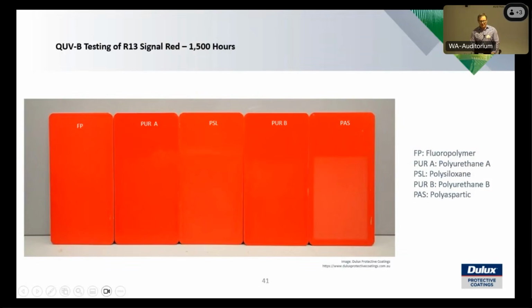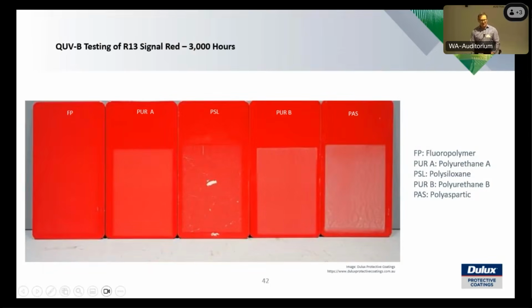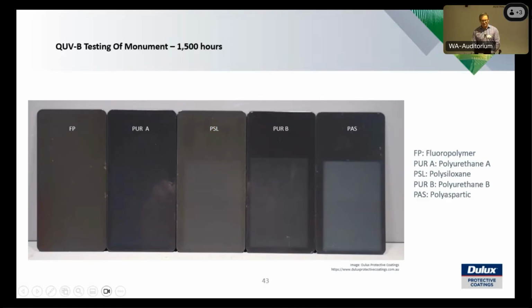We get to the signal red after 1,500 hours. As you can see, that visual there shows the signal red is still looking pretty good with the fluoropolymer. Hardly any change at all, and the polyaspartic is just starting to chalk up a little bit there. The 3,000 hours, all four of those panels except the fluoropolymer. There's a little bit of change in the fluoropolymer. There's a bit of white starting to develop. But in general, the fluoropolymer is still looking very good after 3,000 hours.